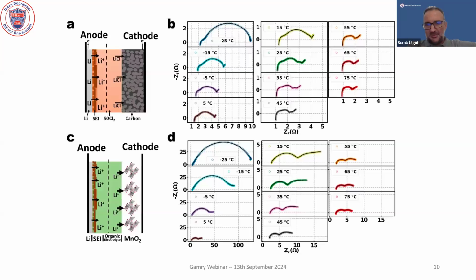So you can see the spectra changes as expected. At low temperatures, the overall impedances are larger, both in the real and the imaginary side, and as temperature goes up, a lot of things change. So the very low frequency semicircle gets smaller super quickly, and then the high frequency semicircle stays about as it is as temperature goes up.